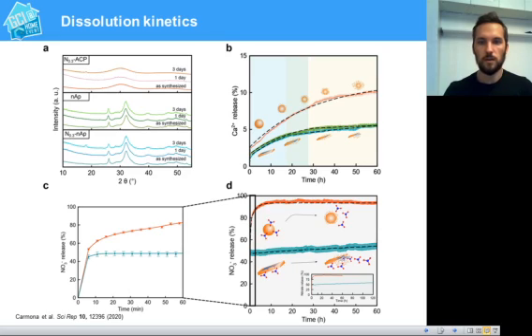The first one, in the first hours, is much similar to that of the amorphous material, and this can be interpreted as the partial dissolution of the amorphous phase located in the width and length of the plates. Whereas the calcium release slows down at longer time, and this dissolution may be due to the exposure of the basal faces of the plates and to the dissolution of the crystalline core.